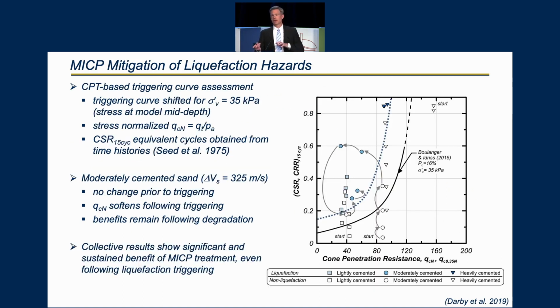So collectively, we have tracking of shear wave velocity, we have tracking of the dynamics, we have tracking of cone tip resistance, and we can stitch these together and look at them in the context of a common liquefaction triggering curve with the Boulanger and Idriss. And so the plot you're seeing here on the right-hand side, that triggering curve is normalized or shifted for a mean effective stress of 35 kPa, which is the stress in the middle of our model. So we're using stress-normalized cone tip, and we've computed equivalent cycles for the motion following Seed.